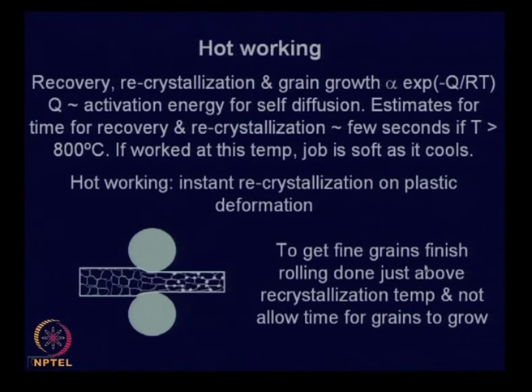And to get fine grain, what you can do, you have to decrease the diffusivity. And how can you do it? That means you finish that rolling at a temperature just above the recrystallization temperature. So, if you can restrict that atom movement, that means your finished rolling is done closer to the recrystallization temperature and you do not allow enough time for the grain to grow.